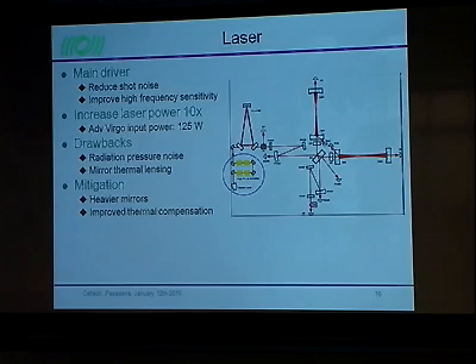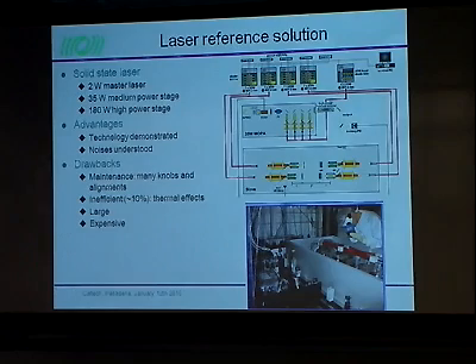The reference solution for the laser is the same as for advanced LIGO, so the use of a solid-state laser which has been developed at Laser Zentrum Hannover. It is a laser that, as you know, is composed of 3 stages, a 2 watt pre-stabilized master laser, then an intermediate power stage made with a power amplifier delivering 35 watts, and finally a ring oscillator injection locked delivering 120 watts and 180 watts.